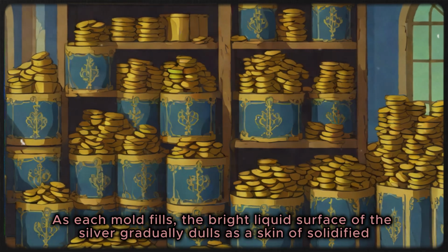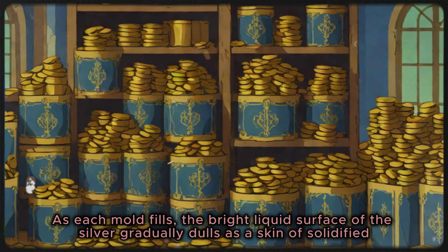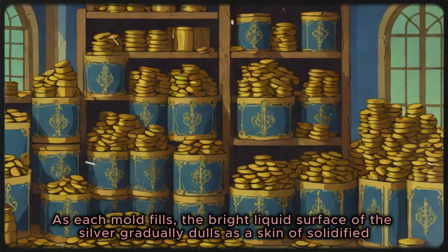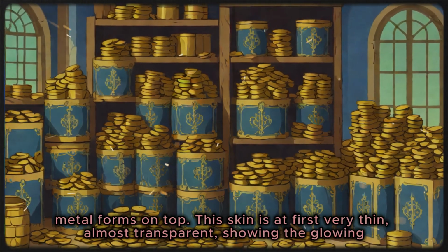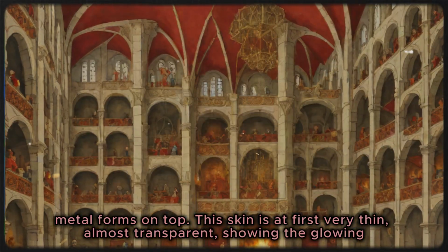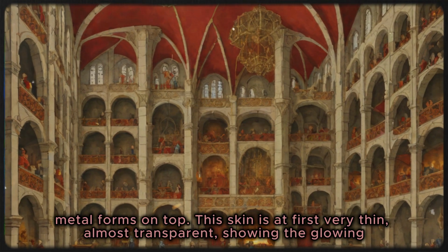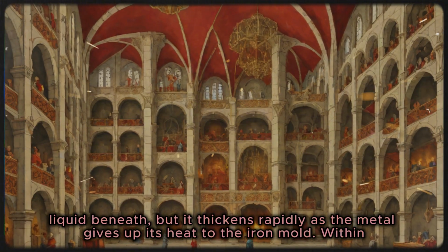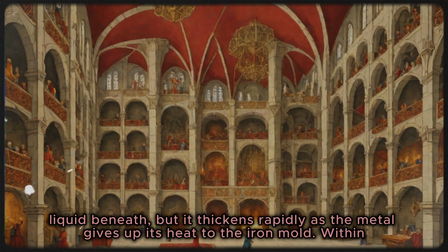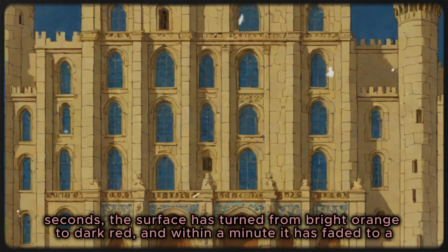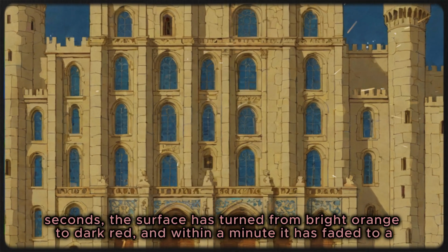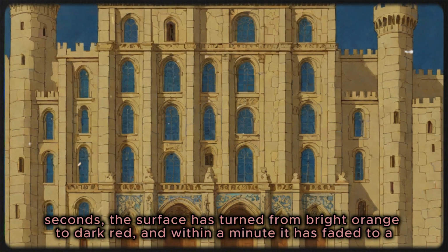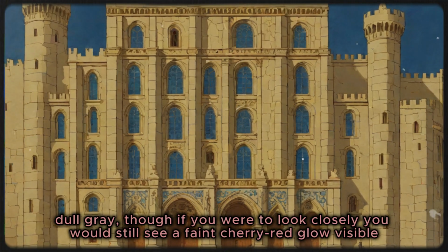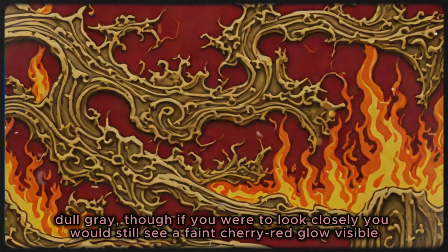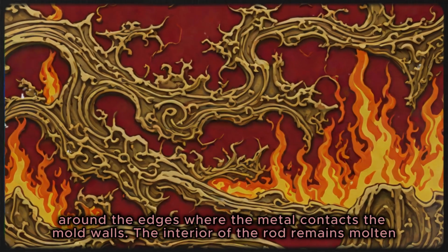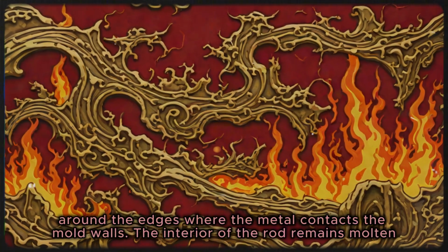As each mold fills, the bright liquid surface of the silver gradually dulls as a skin of solidified metal forms on top. This skin is at first very thin, almost transparent, showing the glowing liquid beneath, but it thickens rapidly as the metal gives up its heat to the iron mold. Within seconds, the surface has turned from bright orange to dark red, and within a minute it has faded to a dull grey, though if you were to look closely you would still see a faint cherry-red glow visible around the edges where the metal contacts the mold walls.